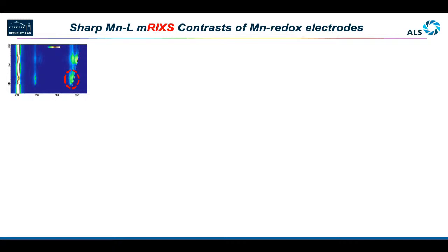Here I said I will not talk about the instrumentation much in my talk, but I do want to mention one thing: we do have lousy resolution. If you have heard the talks in the previous days, our resolution is very low, only about 1,500 resolving power, limited by resources and also real estate, the space at the light source. Although we are improving in the next, hopefully, one or two years, we do have a benefit. Our spectrometer covers 400 to 450 eV of the emission energy in one single shot. So we can pull out all those channels from the so-called partial fluorescence yield, inverse partial fluorescence yield, core-to-core decay. Everything shows up simultaneously.